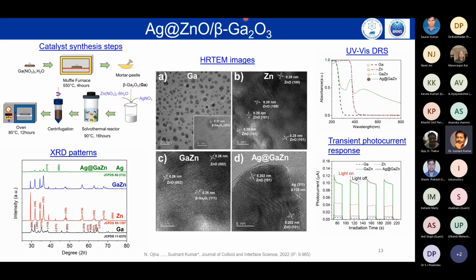And these are the catalyst synthesis steps, which you can see. These are the XRD patterns, which clearly show the presence of silver and the gallium zinc structure, the heterostructure that we have. And these are the HRTEM images, where we can see the different interfaces of the silver and the zinc oxide. Now, in the UV-vis DRS, you can see the increase in absorbance, which is primarily because of the presence of the silver, and there is also a shift in the absorbance spectra. This shift is all because of the drop in the band gap values, which we will see in the next slide.